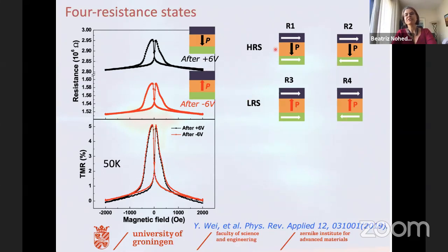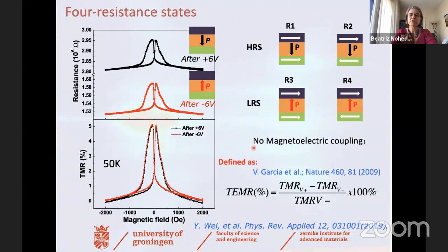Here you see the four different resistance states. However, one surprise that we had is that when you overlap these two TMR loops, you see that they're nearly identical. So this means that the effect of the polarization is basically zero on the TMR. So there's no magnetoelectric coupling as we would expect in a ferroelectric or in a multiferroic tunnel junction. Here is the definition of the TEMR effect, this magnetoelectric coupling, as defined in this paper by Garcia and co-workers. So the TMR with polarization up and the TMR with polarization down, this didn't seem to change.